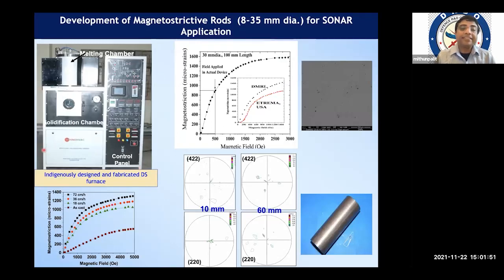And this furnace was indigenously designed by us at DMRL and fabricated by an Indian fabricator. With this machine, we could achieve a magnetostriction value which is even better than the best reported international value in this material. And Etrema USA, the company which is the sole producer of this magnetostrictive material in the world, our values are even slightly better than the values reported by them. And here also we have done detailed microstructural and texture analysis, and then we could realize a big 30 mm dia, 100 mm length magnetostrictive rod.